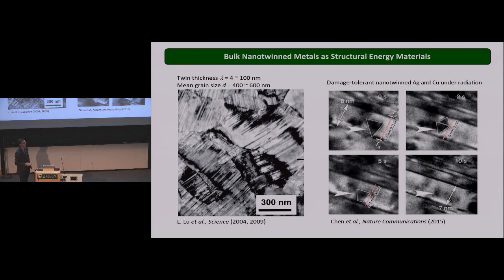And an example of where you can apply nanotwin metals for energy applications is shown here. So that's an example where you take a nanotwin copper material, like this one, and it's exposed to radiation. So similar to the environment you will have in a nuclear power plant. And so the aging of the material in those applications results from the formation of defects, stacking faults. And so this is an example of a defect that could form from radiation. And so what this shows is the twin planes that are shown on the images here will absorb the defect very rapidly as soon as they are formed.